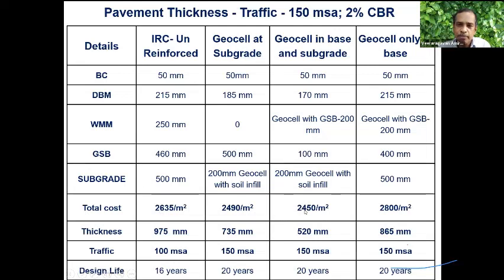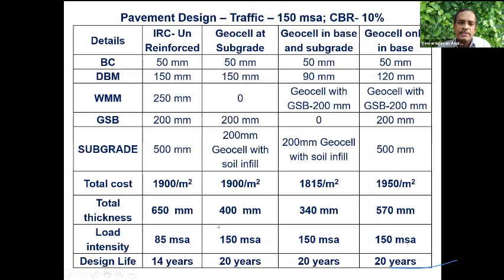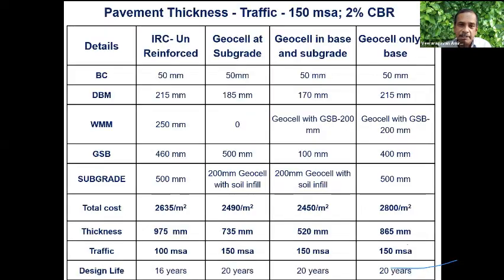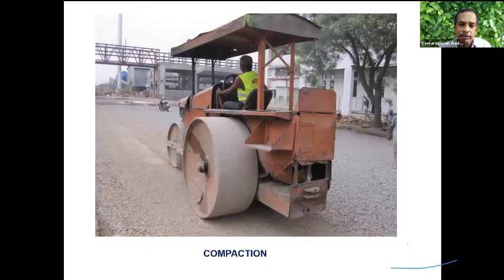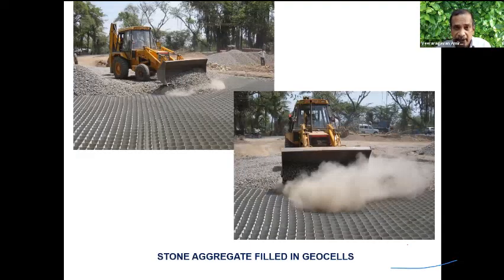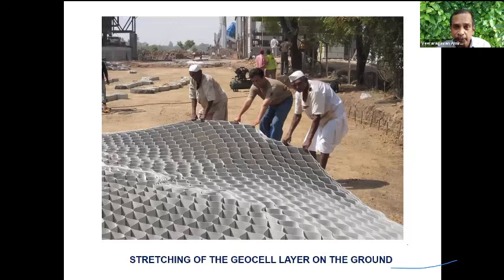Not only for a low CBR, even for a high CBR. Instead of having 650 millimeter, I can bring down thickness to 340 using geocells. They provide the confinement that you need. There are perforations. This enables drainage. As I was mentioning, subsurface drainage is possible.